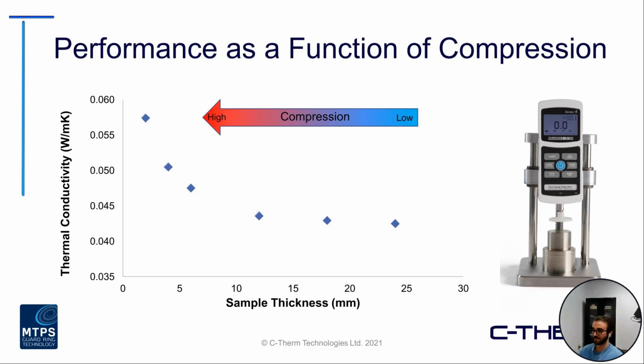And you can see as the compression was at its highest point, so at the far left, this resulted in the highest effective thermal conductivity. Again, because you're pushing out that air, having more of that material contact, adding better pathways for heat conduction to occur. Then as you go to a higher and higher sample thickness, a lower compression state, that result starts to decrease. But here you can see that initially it was very high, and then it dropped quite steeply, and then it began to flatline a little bit near the end there.